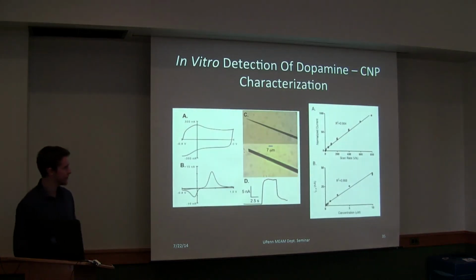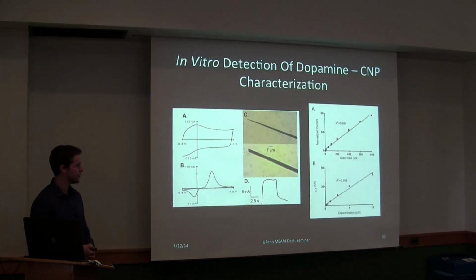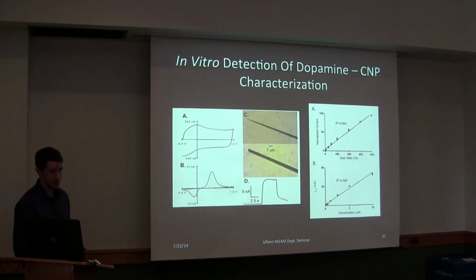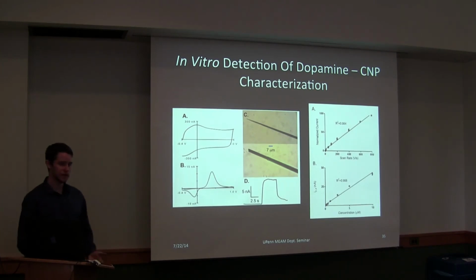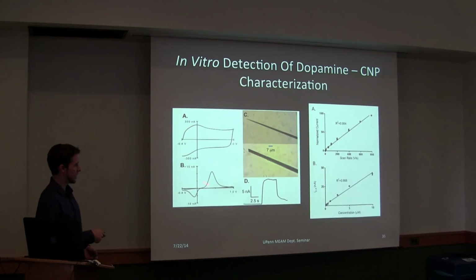So we started this collaboration and sent them some electrodes. They started characterizing them. Here is a quick comparison between the size scale of carbon fiber versus a carbon nanopipette. This is what the background current looks like when you initially take the measurement, with a very large capacitive charging current. But after you do the background subtraction, you get very clear redox peaks corresponding to the oxidation and reduction of dopamine, and you can look at the current signal over time corresponding to this characterization.